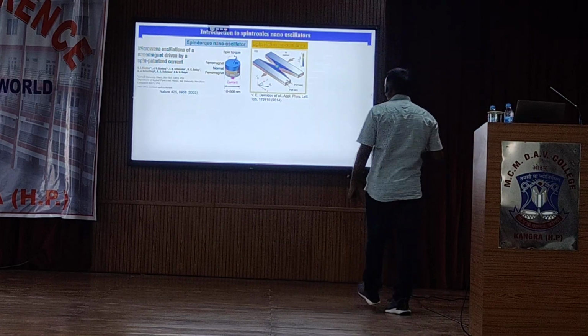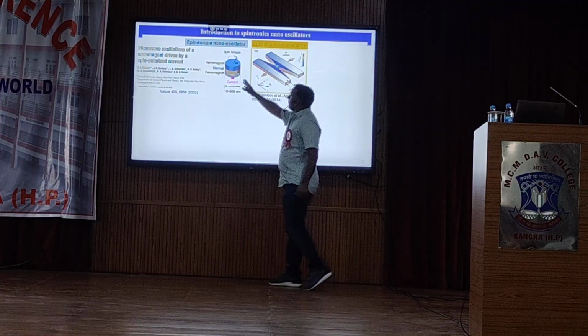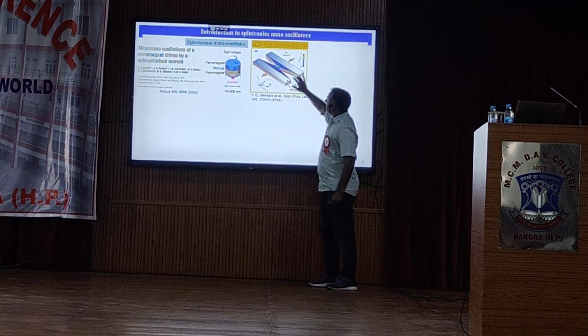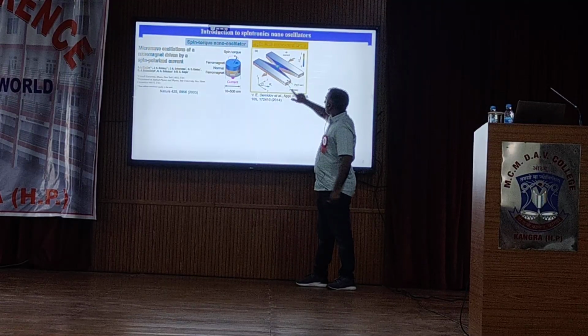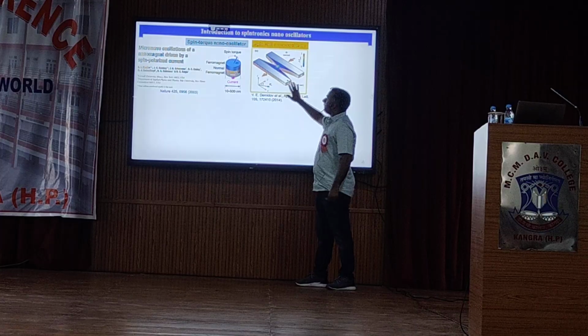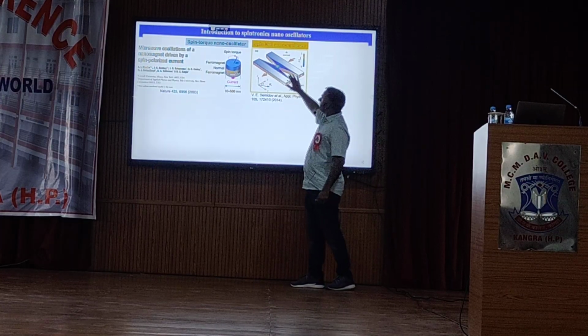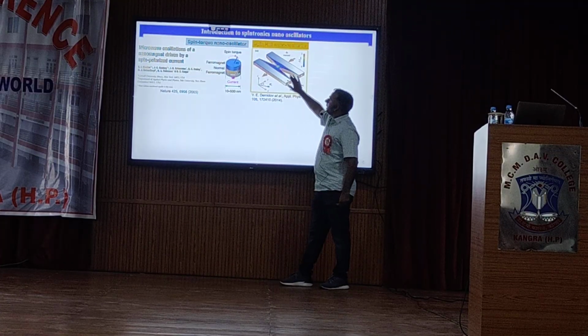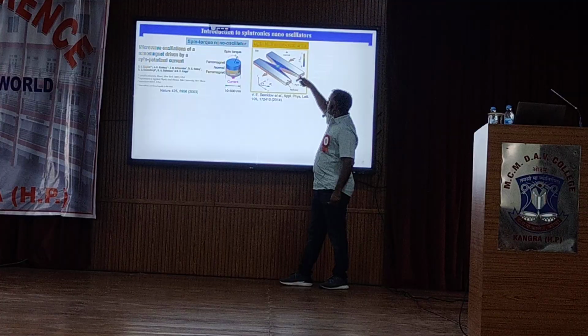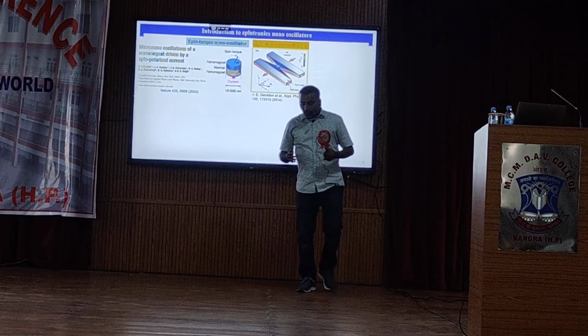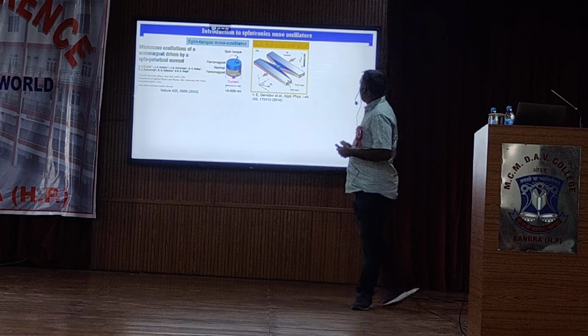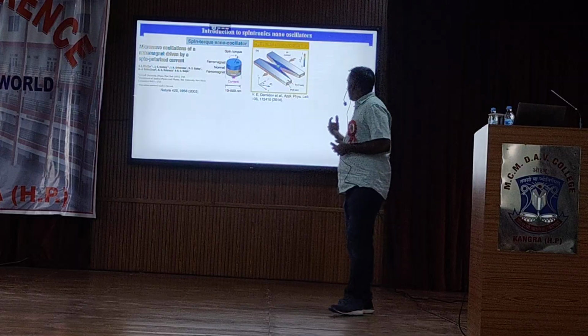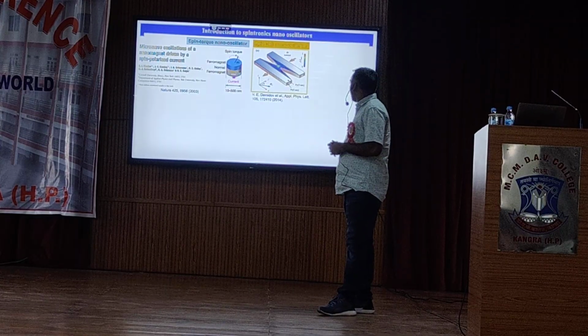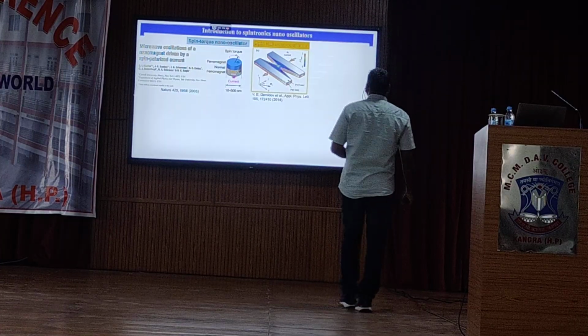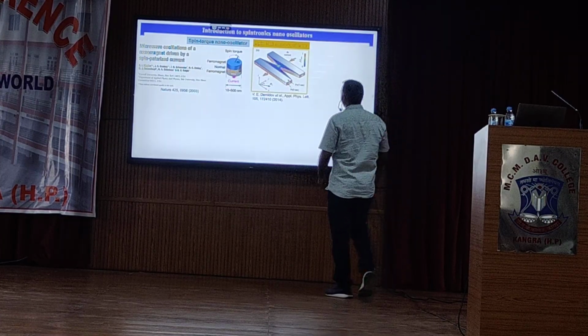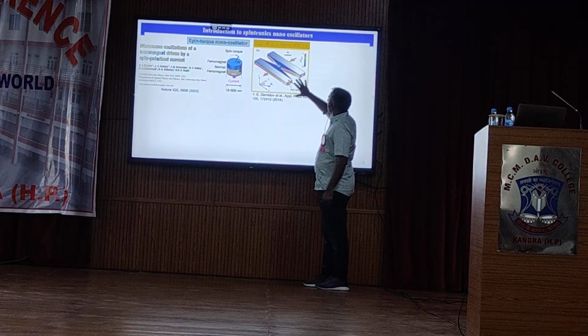Then a simpler device was proposed by Demidov et al. Rather than having this vertical structure, in this kind of oscillator, which we call spin Hall nano oscillators, we have only two layers: one magnetic layer, here we are using permalloy, and another non-magnetic layer, which is platinum. The benefit of using this kind of device is that it is a simple bilayer device, and you just need to pass the current in the platinum layer. Platinum, because of its strong spin orbit coupling, will generate a spin current that passes through the magnetic layer, and that spin current will exert a torque on the magnetization of that layer, and we see the magnetization dynamics. The micromagnetic simulations from this work can be seen here.